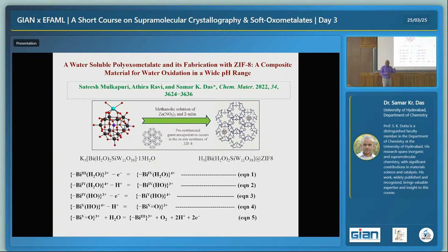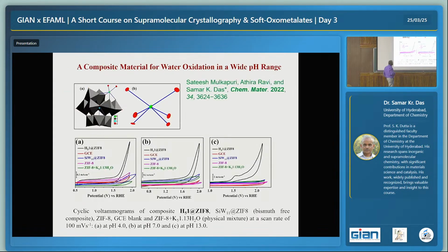Then we wanted to check really the electrochemistry, water oxidation. Now you see, a very interesting thing happens. We can use a very wide pH range, from pH 4 to 7 to pH 13. At pH 13, a polyoxometalate, you cannot imagine, it will decompose. It will just come back to monomeric oxo molybdate or tungstate. But here you can do even 100 cycles at pH 13. You can do 500 cycles at neutral pH. You can do even 1000 cycles at pH 4.